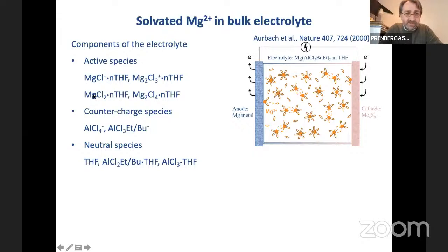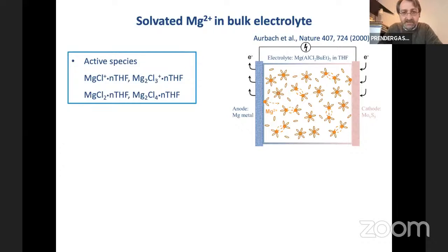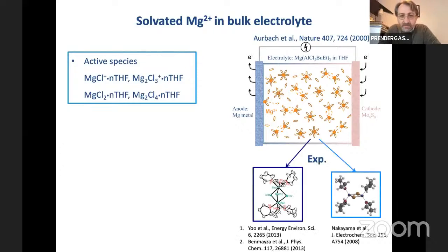You had various different species that might be present and proposed to be active, these contact ion pairs and triples of magnesium with chloride, and then other countercharge species that were even more complicated with some organics, and then you have some solvent. But we started, thinking about this and saying, let's focus on the active species. And then already there was some controversy talking about different experiments that could see different coordinations of magnesium in the electrolyte. Some were done by freezing the electrolyte after the effect to make a solid crystal and then analyzing that, which is obviously not the same, and then other efforts that were done on real liquid samples.